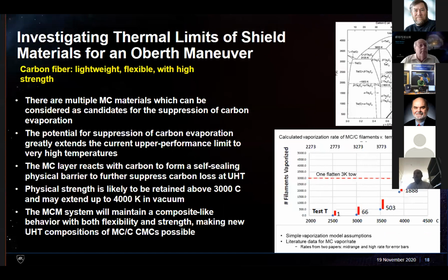And again, a similar chart shows that there are multiple materials. I think this is tantalum carbide up here, the vapor curve, but you're seeing temperatures up in the 3,000 to 4,000 range. So there are materials that get up this hot. Again, with proprietary processes and materials, we're going through the process of using those materials to suppress the evaporation of the carbon, which extends its operating temperature to much higher levels. Much work needs to be done there, but there's potential there.